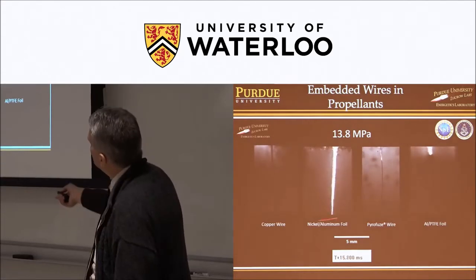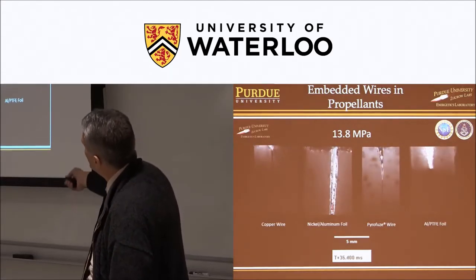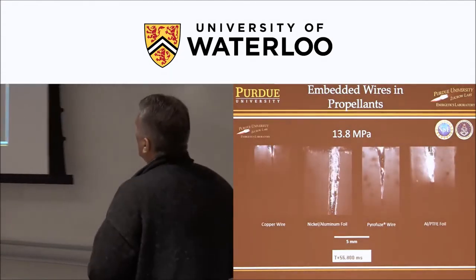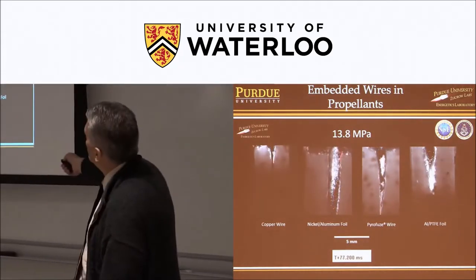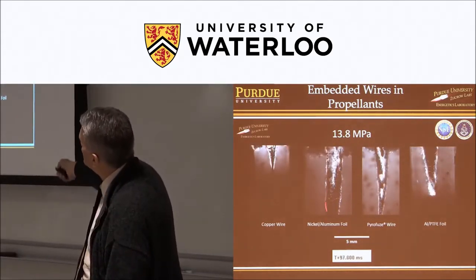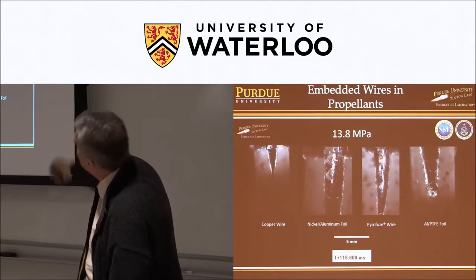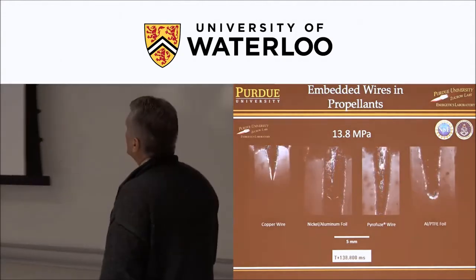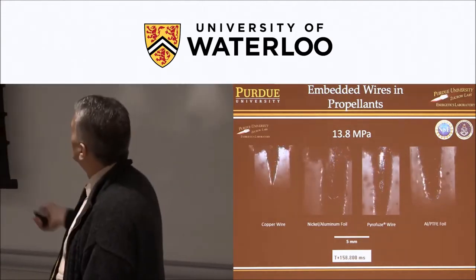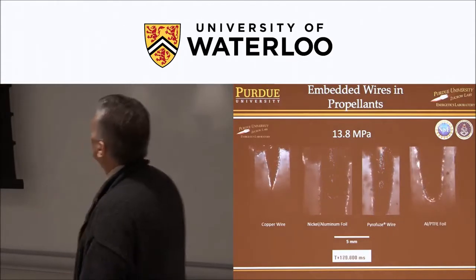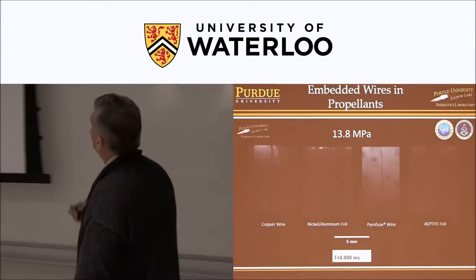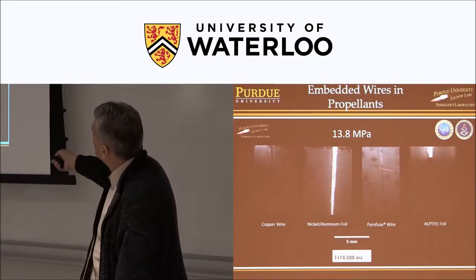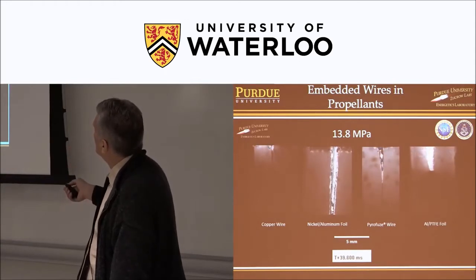This is the nickel aluminum foil. It's a nanostructured, layered material, and it's going much, much faster. You really have a hard time seeing the V structure. It shoots down through the propellant. Pyrofuse is a little bit slower. And our aluminum Teflon foiled material is pretty fast, but maybe a little bit slower than the pyrofuse.